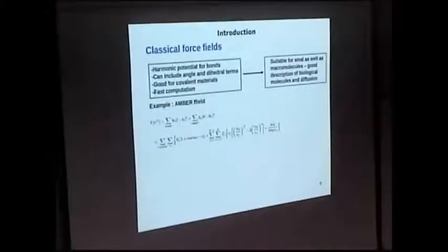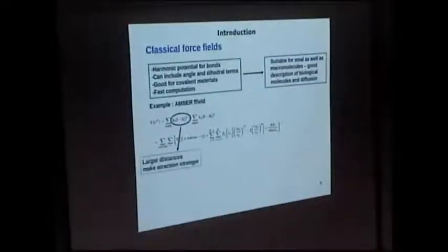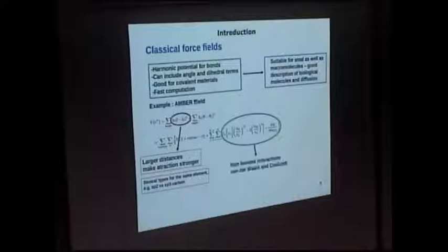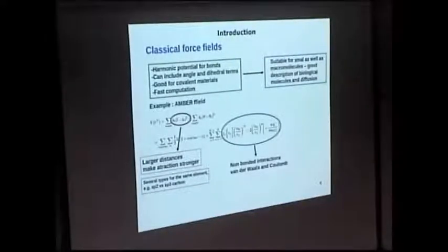Then we have on the other side classical force fields that are not reactive in this case. And for this kind of description, we have an important feature here. We have the potential. This potential is made with several contributions. One, in this example, a spring force term, angles between bonds term, a torsion term, and a non-bonded interaction term that includes Lennard-Jones and Coulomb.